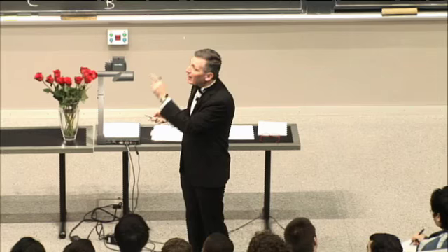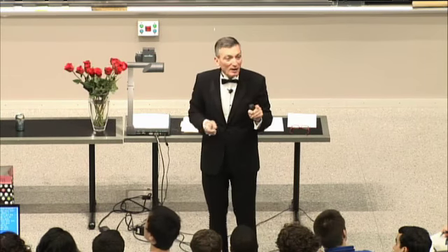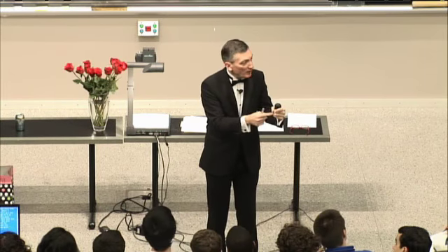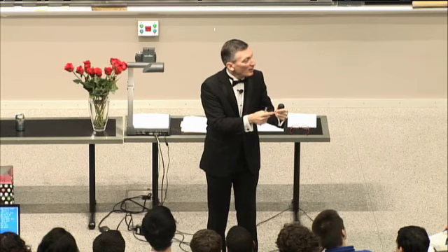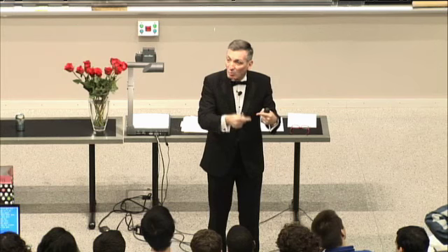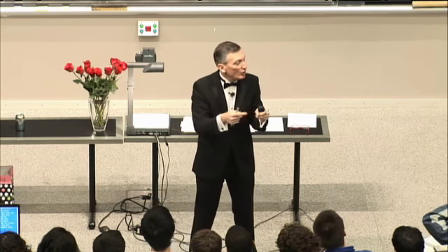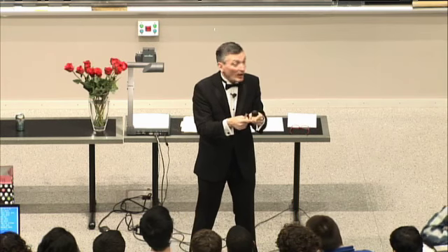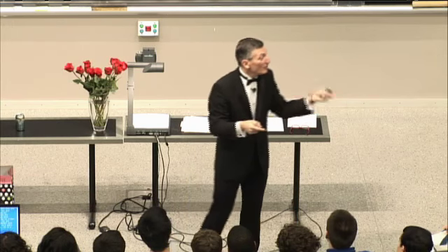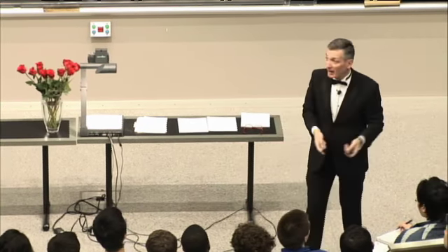And the way they tell cubic zirconia from diamond is they actually put a couple of tips on either side of the stone, and they heat one tip and measure the time lag for the thermal wave to get to the other tip. And if it's cubic zirconia, it takes a long time because cubic zirconia is an insulator. If it's diamond, it's almost like metallic conduction, and that's how they can tell a fake diamond from a real diamond.